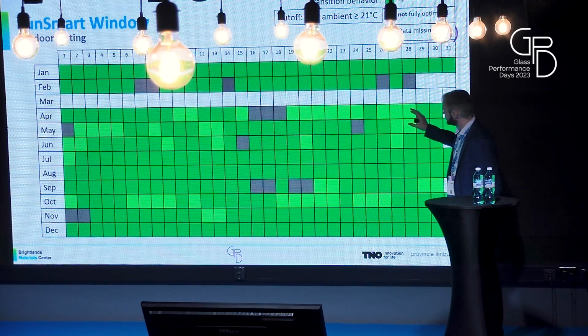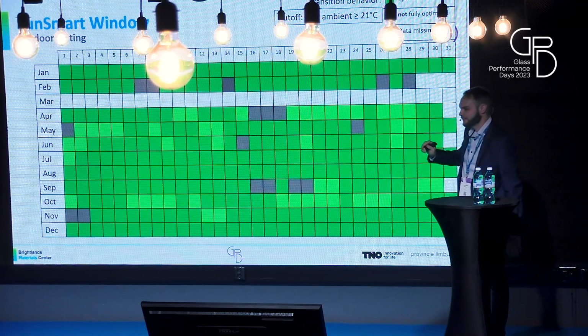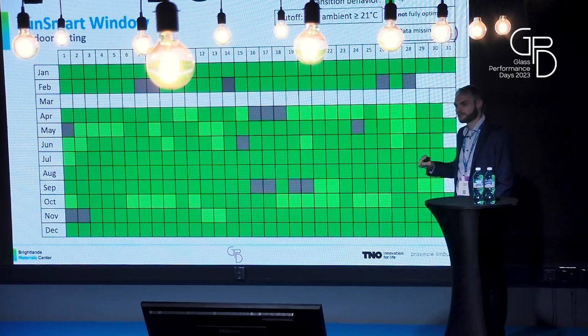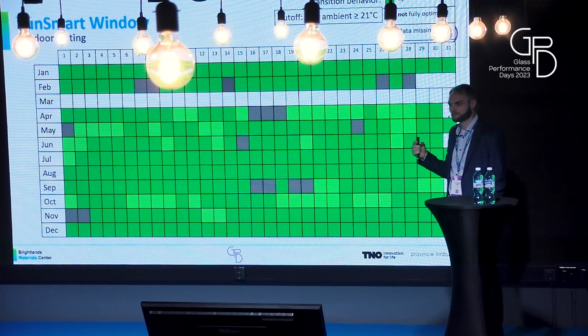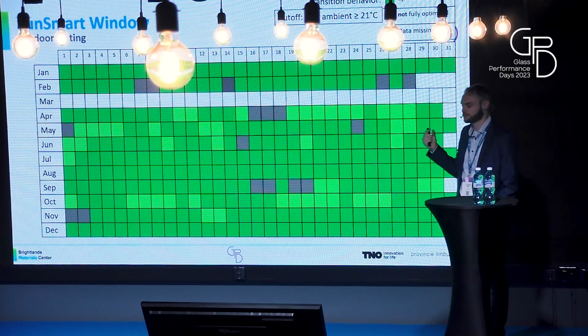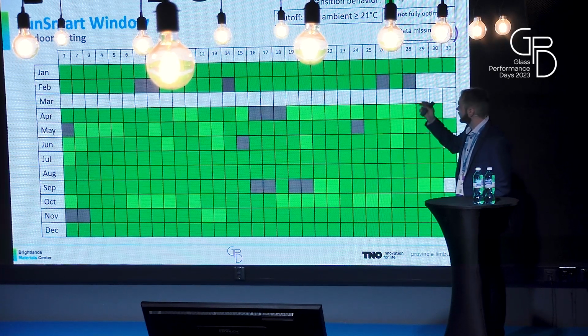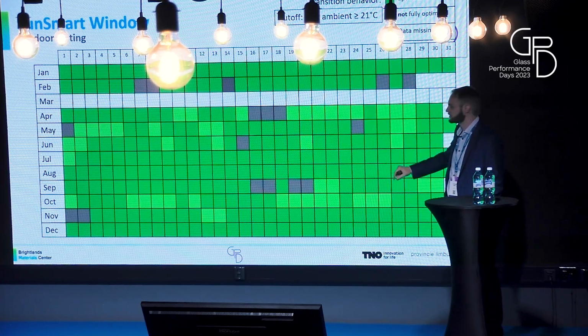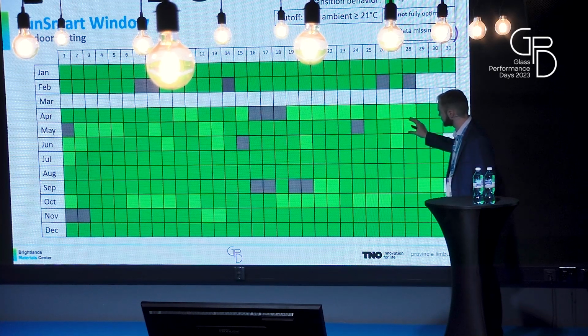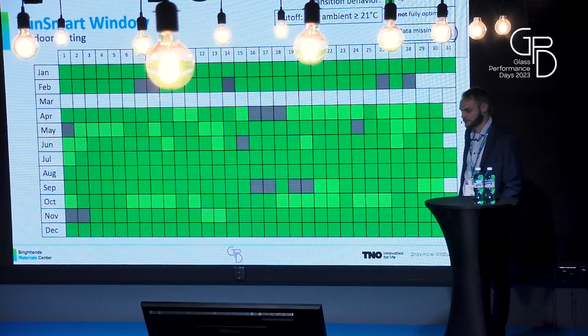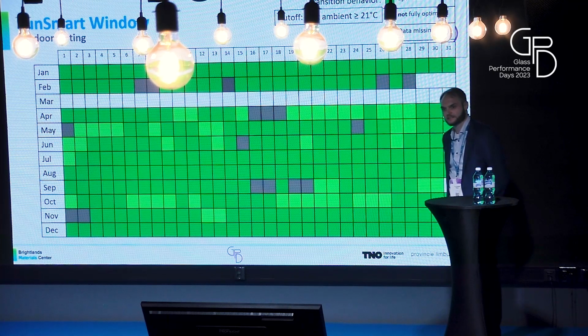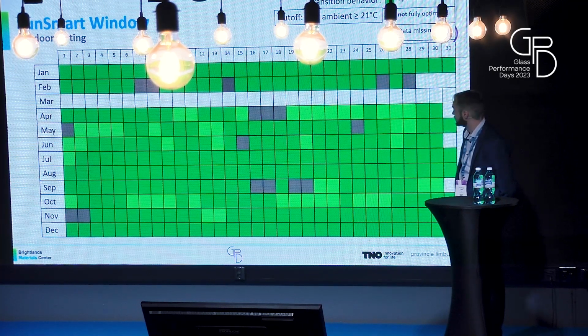In autumn and in spring, we see that there are some days where we have a switching material, but the ambient temperature did not exceed 21 degrees. So if we now change that cutoff to 20 degrees, then you already get rid of most of these light green squares, and it looks like it's behaving better. So it also depends on the cutoff.